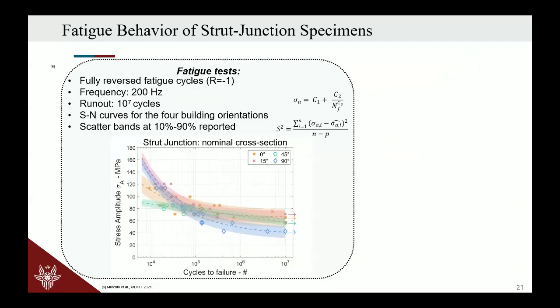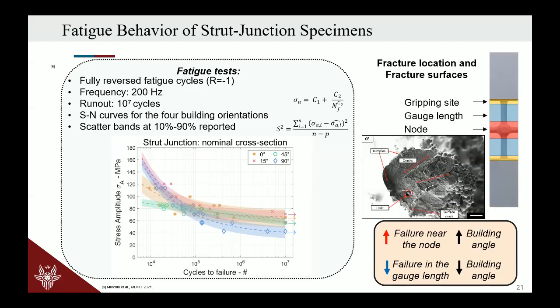Also there, we made a very huge experimental campaign that is only summarized with this slide for lack of time. But the results have shown that the failure near the node happens when we increase the building orientation angle, and the failure in the gauge length happens statistically more frequently when we have a building angle that is decreasing.